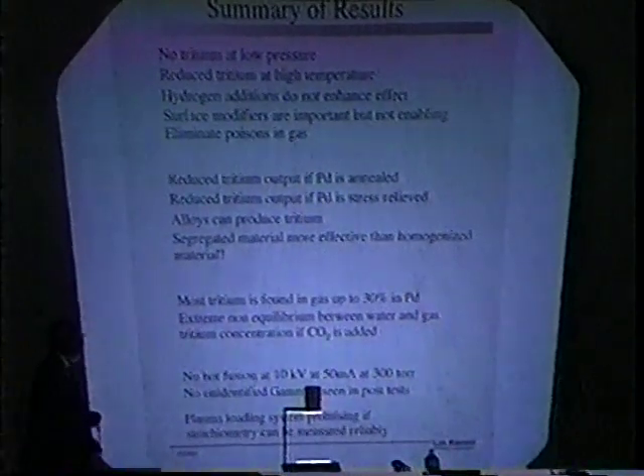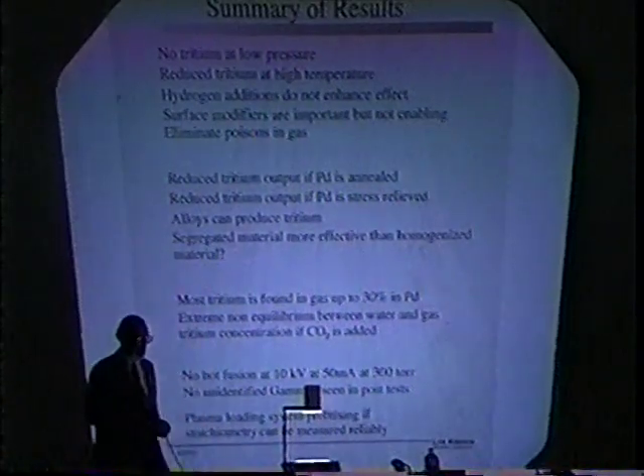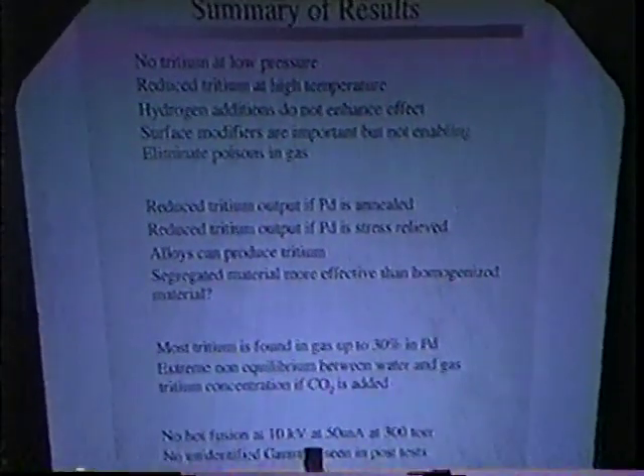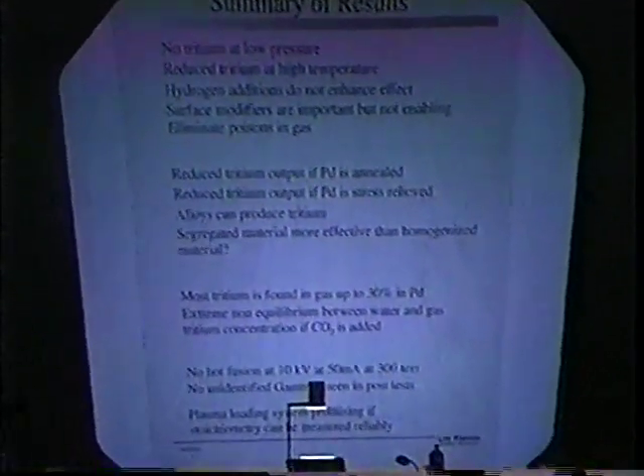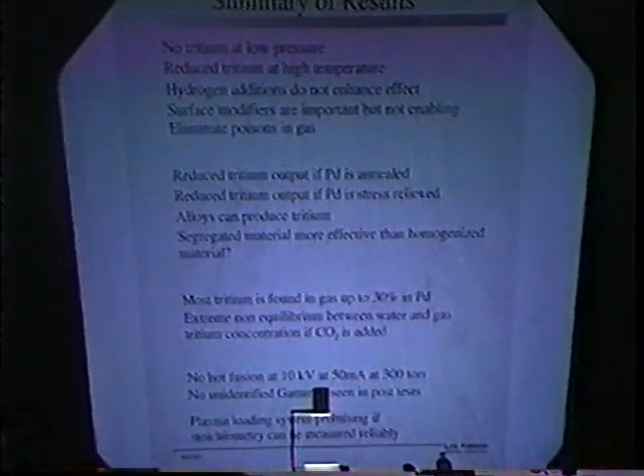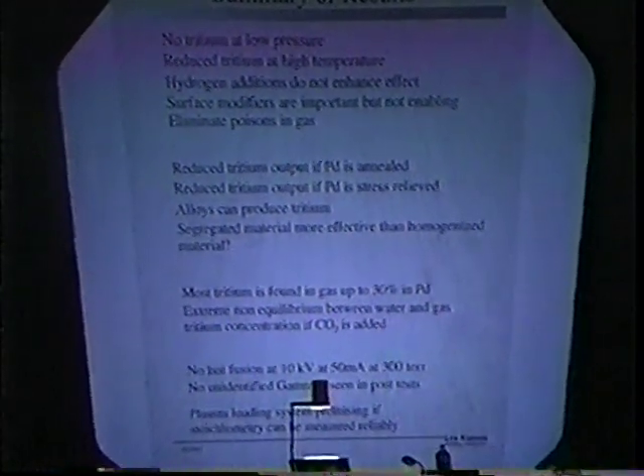Reduced tritium output if the palladium is annealed. Now, that's rather interesting. That's saying that the morphology of the palladium is exceedingly important, and you need to have palladium that is unannealed. Reduced tritium output if the palladium is stress relieved, and so obviously it's the annealing that is causing stress relief, and so that's the relationship. Alloys can produce tritium. It isn't clear at this point whether they do it better than pure palladium.